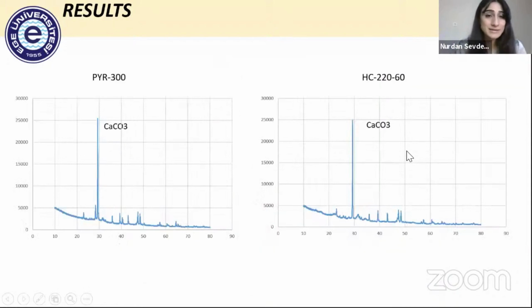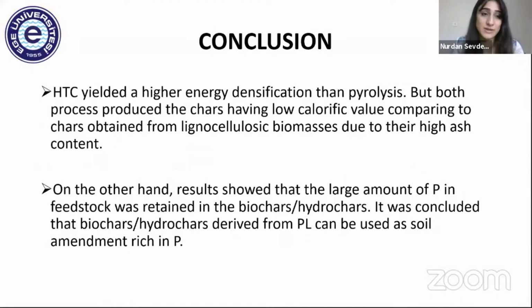We also made the XRD analysis of the selected biochar and hydrochar. When we examine the analysis, we can see calcium carbonate crystal. So there is no phosphorus crystalline in the structure.